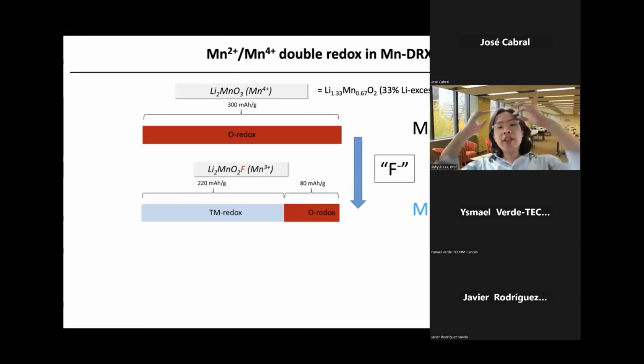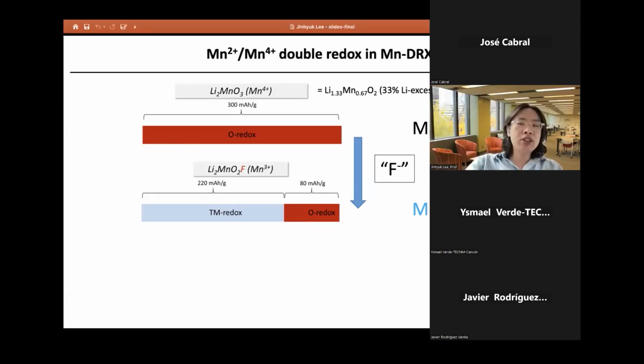But now let's imagine we replace one of the oxygen 2 minus ions with a fluorine 1 minus anion. Instead of O3, we go to the O2F composition. Because the total anion valence has changed: oxygen is 2 minus, times 3 is 6 minus. But if you go to O2F, the total anion valence is 5 minus. So the total cation valence also has to change from 6+ to 5+, right?